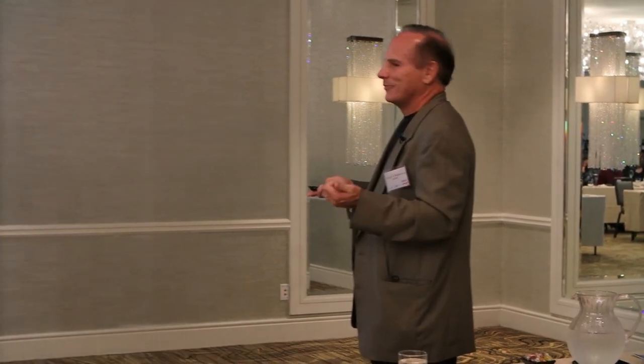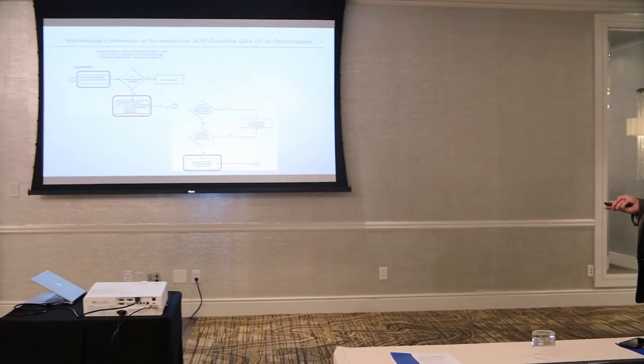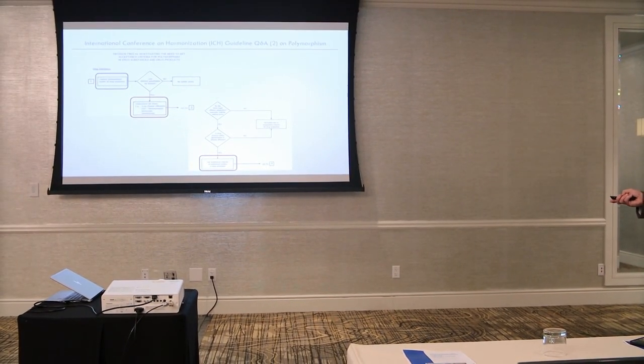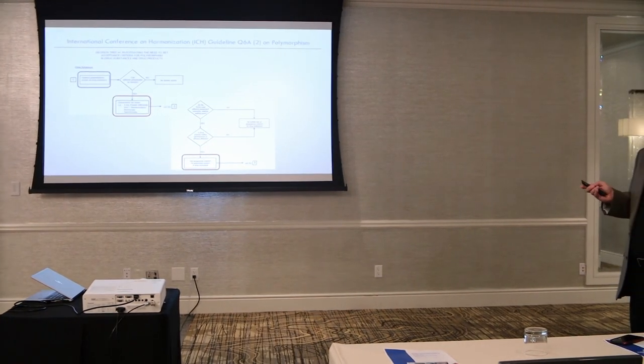There are supposed to be two identification techniques. Once you've identified the forms and understand their thermodynamic relationships, you can develop a process that produces a single form. You'll use a qualitative technique — oftentimes X-ray powder diffraction. You typically need two analytical methods for identification of your API, and you can substitute one: X-ray powder diffraction is one of those. Alternatively, it can be FTIR, which is a little less discerning from a crystallographic standpoint, but powder diffraction works very well for this.